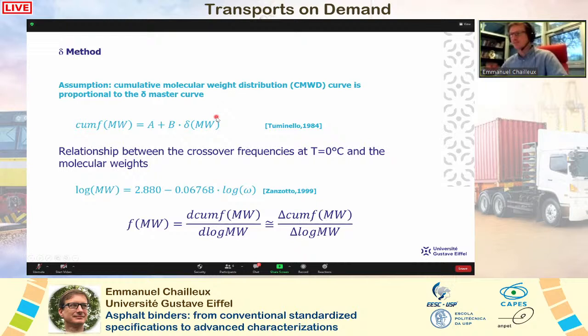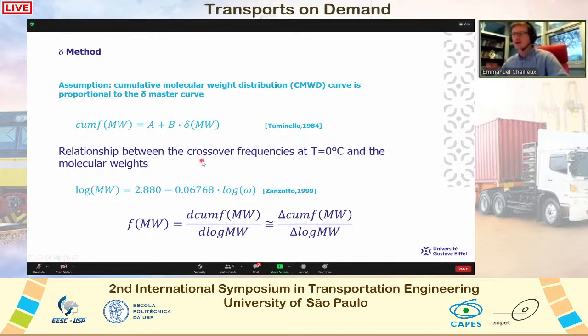But in order to have access to the molecular weight distribution, we need to transform the frequency of measurement into molecular weight, and this relationship was established by Zanzotto 20 years ago. He built this type of relationship where we can calculate the molecular weight according to the frequency used. At the end, the distribution of molecular weight can be calculated by differentiating the cumulative molecular weight. So it means that to have this distribution of molecular weight, we just need to differentiate the phase angle according to the frequency or to the molecular weight. So at the end, it's a very simple way.